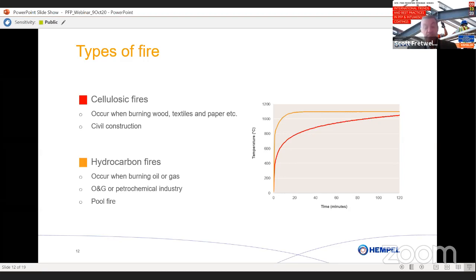Regarding the fire time versus temperature, on the graph on the right-hand side of the screen, you can see here an example of the cellulosic fire curve in red. And you can see straight away, it's a more gradual fire curve. And it takes longer to achieve its maximum temperature, which is around 1100 degrees C in 2 hours. Whereas the hydrocarbon curve in orange achieves its maximum temperature much quicker, maybe 1100 degrees in 10 to 15 minutes, then maintains it for a given period of time. You can see from the two graphs that the cellulosic curve is less onerous, and this is the fire type we will be discussing and concentrating on today.